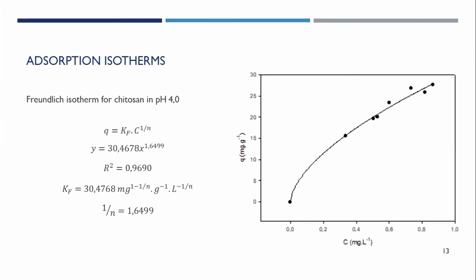The Freundlich equation at a pH value of 4 shows the Freundlich constant to be 30.4768 and the exponent 1 over n to be 1.6499. While the exponent did not show significant change, the Freundlich constant had a major increase, indicating that the decrease of pH favors the adsorption rate for Chitosan.